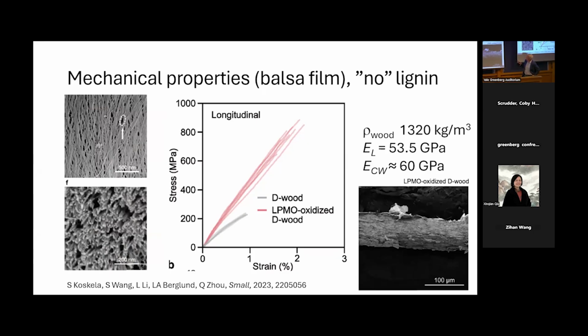And we get quite high density, and the modulus of the material is 54 gigapascal, and of the cell wall then, it is 60 gigapascal. So we're really approaching, I think, what is technically possible by controlling the nanostructure of the cell wall. And I think this is one very important aspect. Even though we're dealing with large structures, beams, we have unique possibilities here because we can tailor the nanostructure and we don't need to assemble a material bottom up. We can utilize the existing nanostructure from nature and try to manipulate that for our purposes.